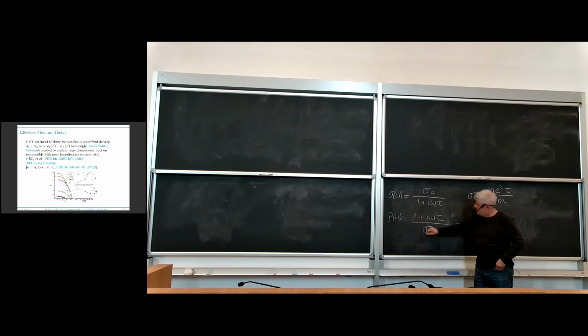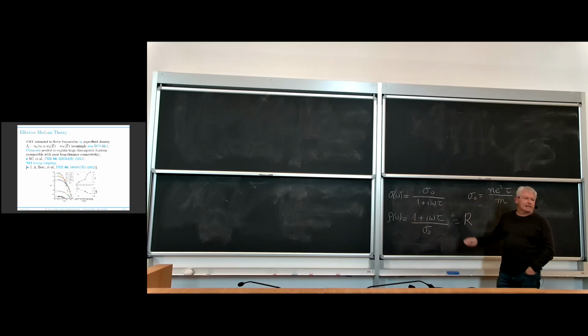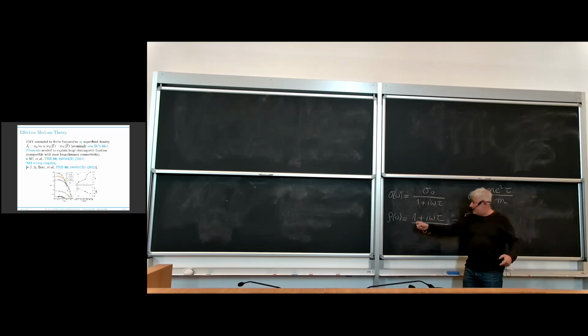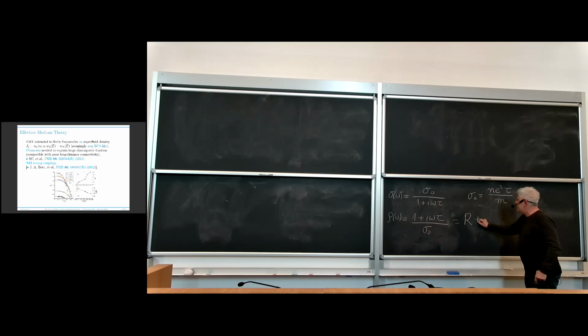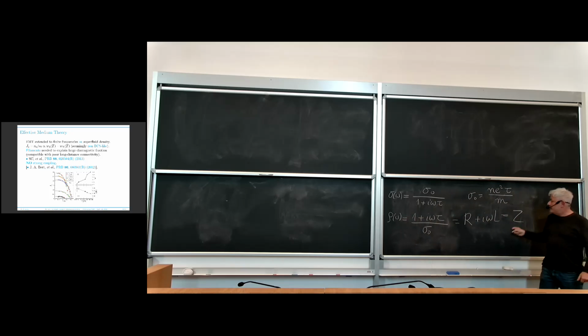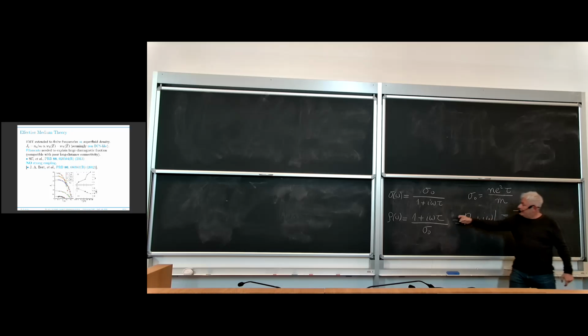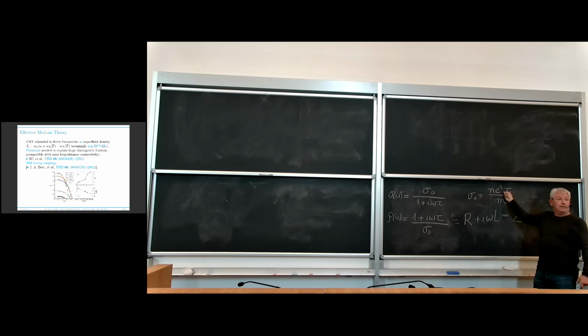Now, this is much easier to interpret because now you can read off this formula the real part and the imaginary part. The real part is just a resistance per unit length, per unit whatever. And the imaginary part is an inductance. This is an impedance whose real part you can interpret as a resistance and whose imaginary part you can interpret as an inductance. So you have the response of a complex impedance with a resistance and an inductance.